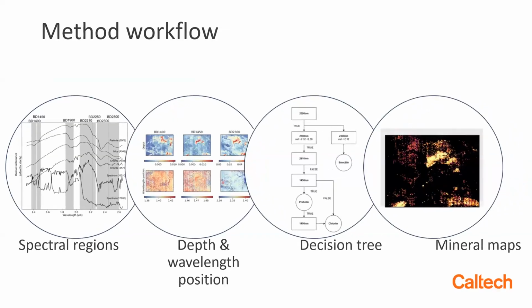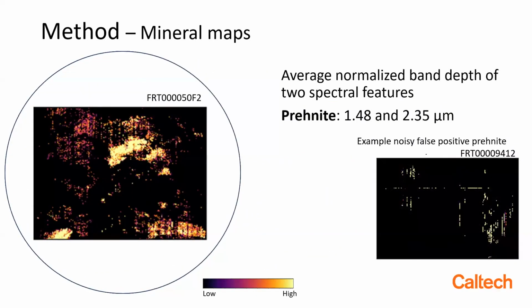So this is the final outcome for one of these images, indicating the likelihood of prehnite. The warmer colors, the more yellow, the higher the confidence and also the higher the presence of the features of prehnite. It's a normalized average between the 1.48 and the 2.35 features. On the right, you see a false positive detection. So we have to deal with some noise, and therefore we still do a manual check with the spectra to see if it is prehnite or not. Next slide, please.